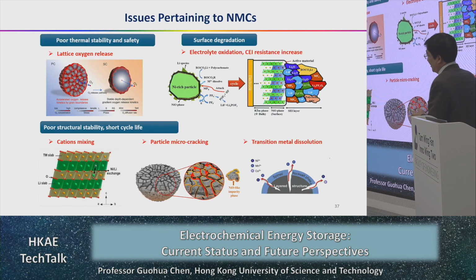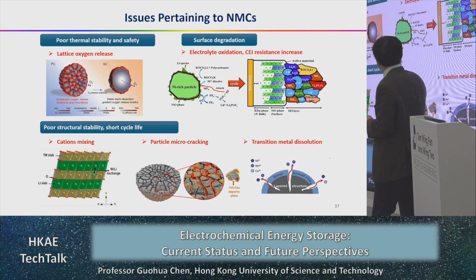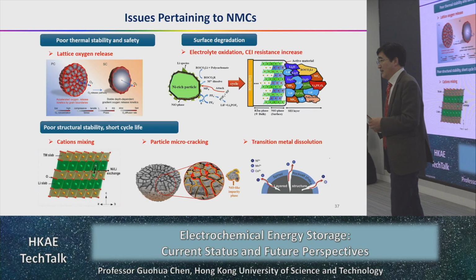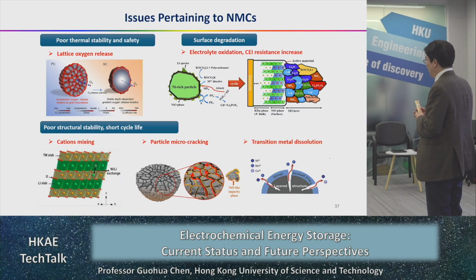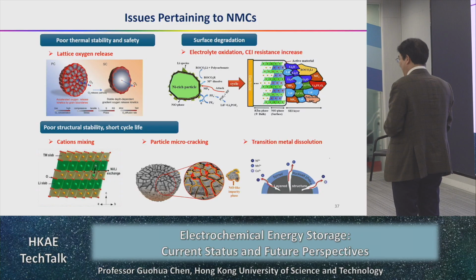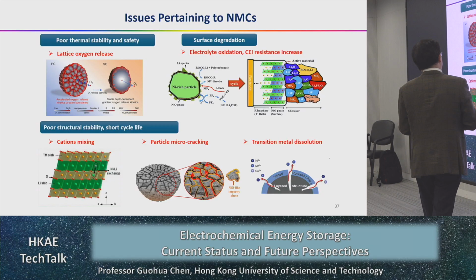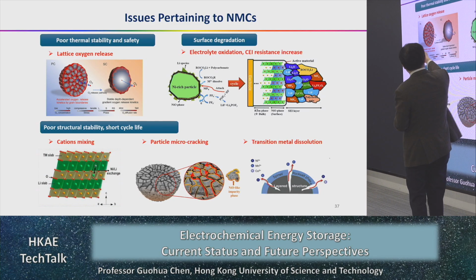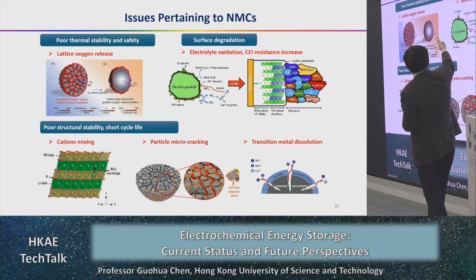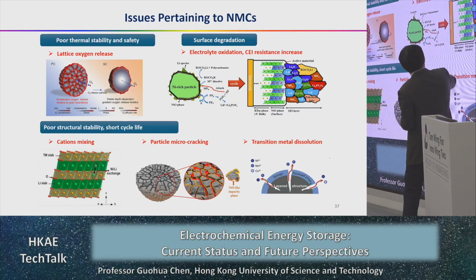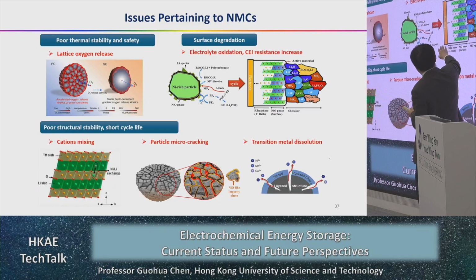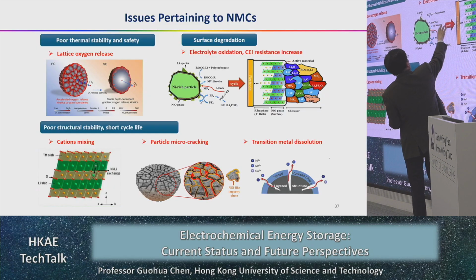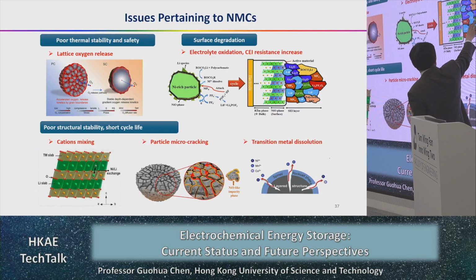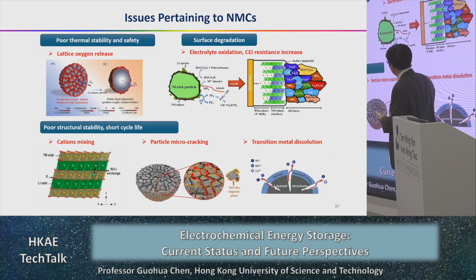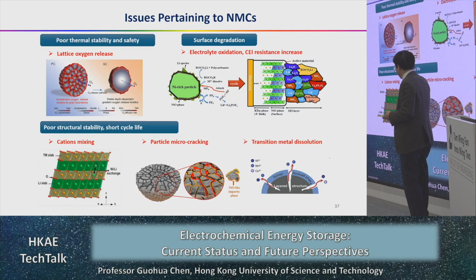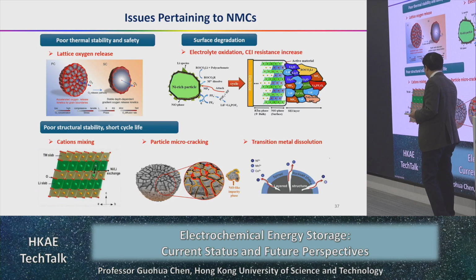And why? NMC has high capacity but does not compete well with LFP because it has a few issues. For example, poor thermal stability, and the surface degradation can easily lead to electrolyte oxidation, CEI formation like that, and also poor structural stability. At the beginning, you have something like that.